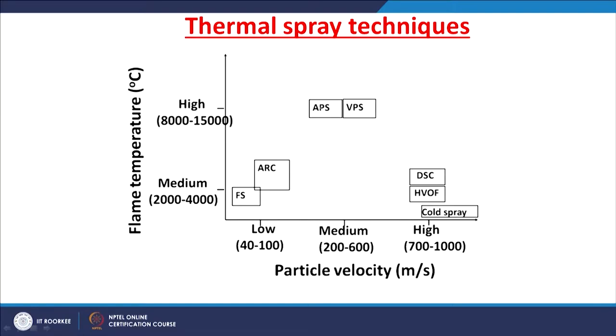The thermal spray techniques include plasma spray techniques — either atmospheric plasma or vacuum plasma — arc technique, flame spray technique, detonation spray coating, and high velocity oxy-fuel. The flame and arc spray techniques develop a temperature in the flame of around 2000 to 4000°C, but particle velocity is low — 40 to 100 meters per second.